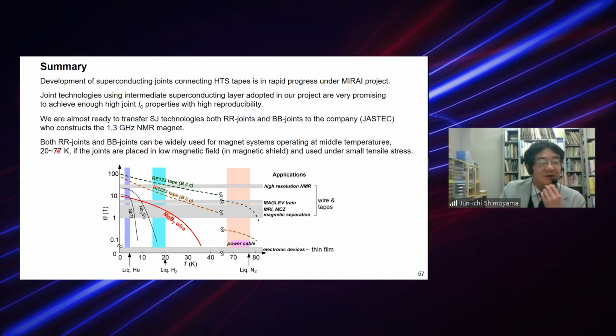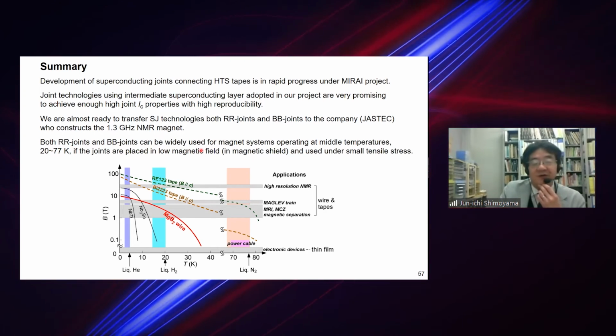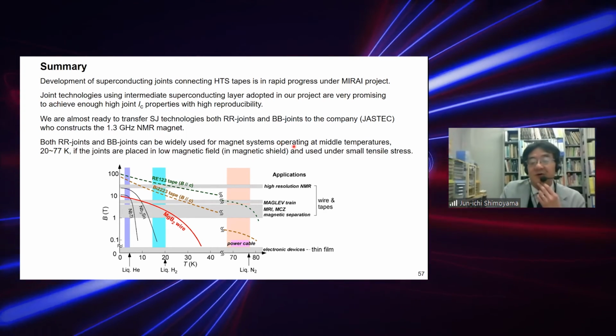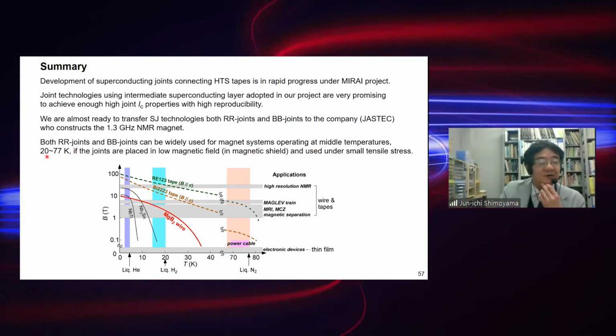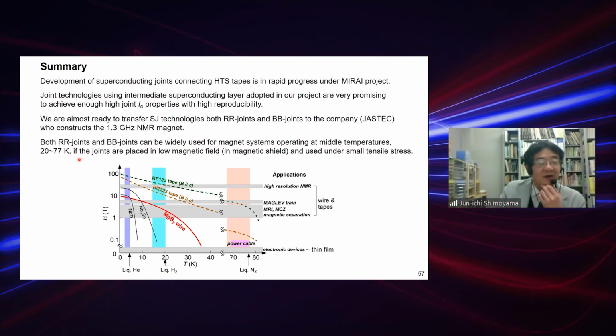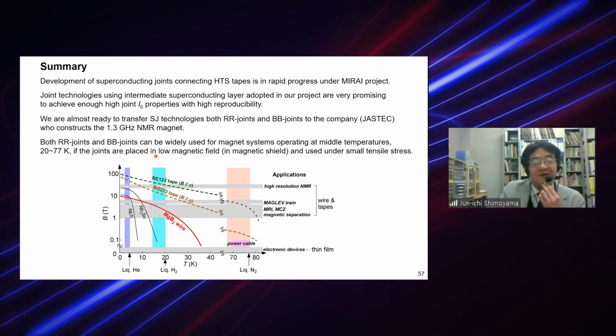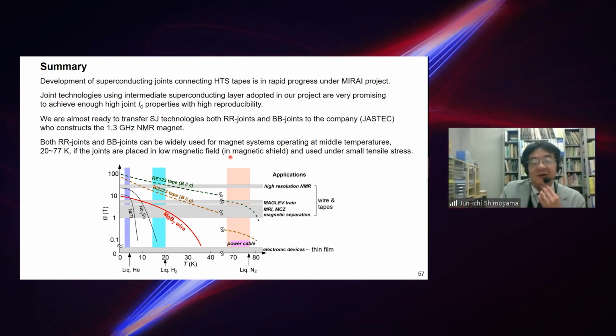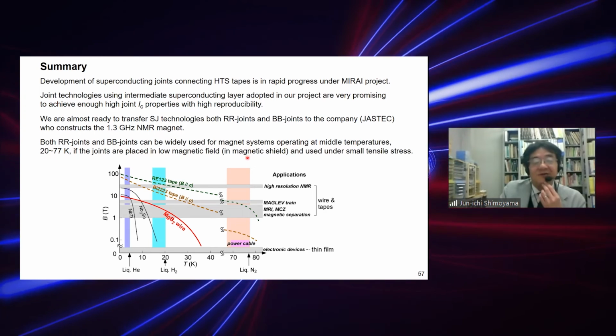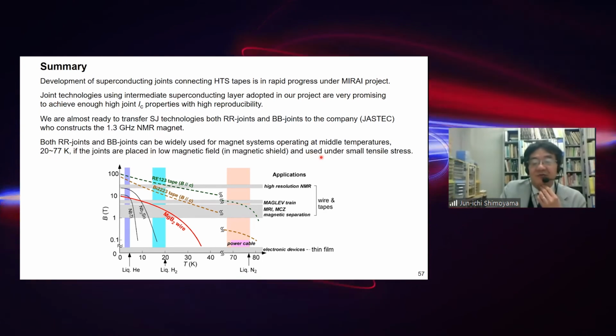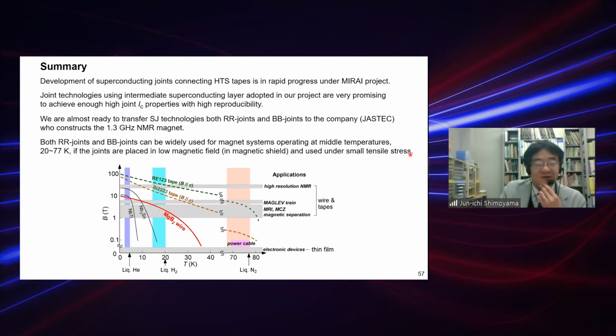And both RR joints and BB joints can be widely used for magnet systems operating at middle temperatures, 20 to 77 Kelvin, if the joints are placed in low magnetic field and used under small tensile stress.